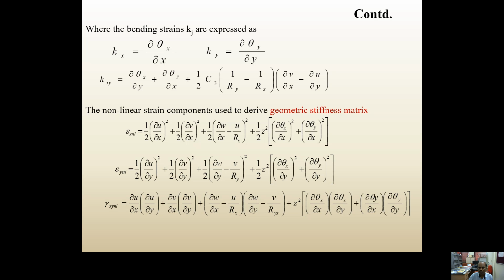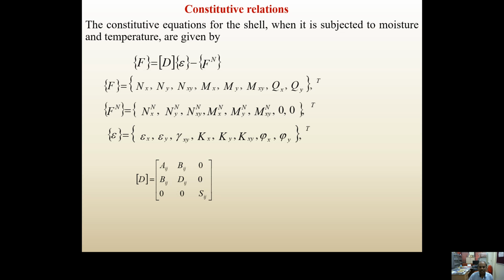This is the nonlinear strain components used to derive the geometric stiffness matrix due to the mechanical and non-mechanical loads. As you can see, there is a force component F^N. So F are the normal forces Nx, Ny, Nxy, Mx, My, and Mxy, Qx, Qy. These are the components normally we experience in composite forces. The first three are the in-plane forces, the next three are the bending forces, and the Q terms are the shear forces. This covers to d epsilon. D is the constitutive relation, and F^N is the force developed due to hygrothermal condition. This component comes into the picture when any structure is subjected to hygrothermal condition. This is reflected in the F equation as well.